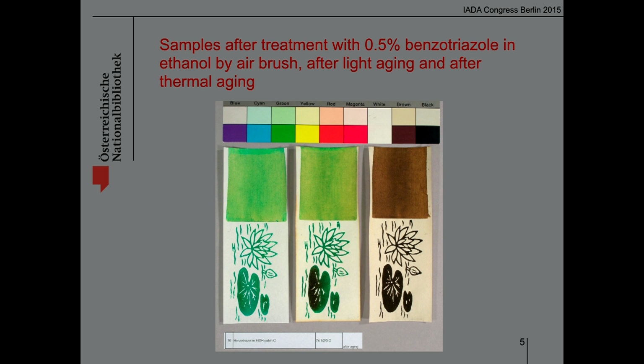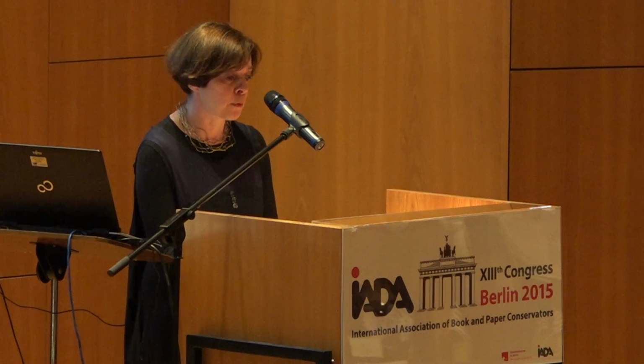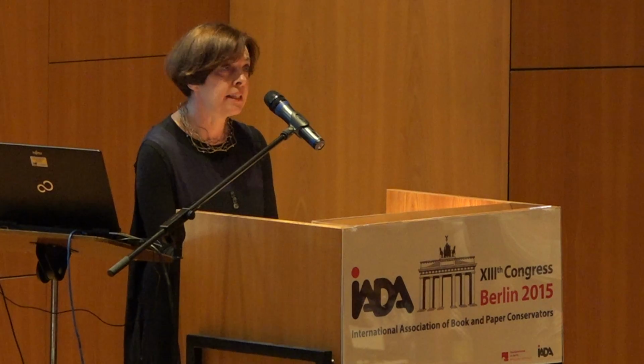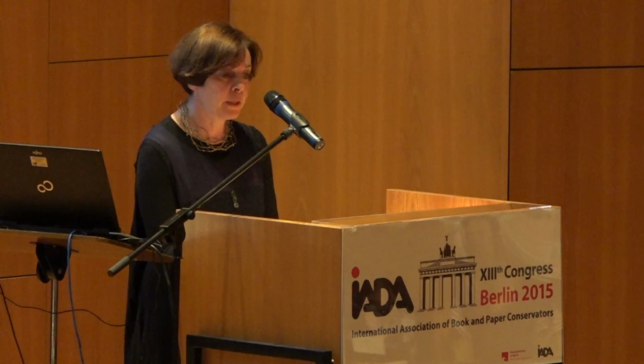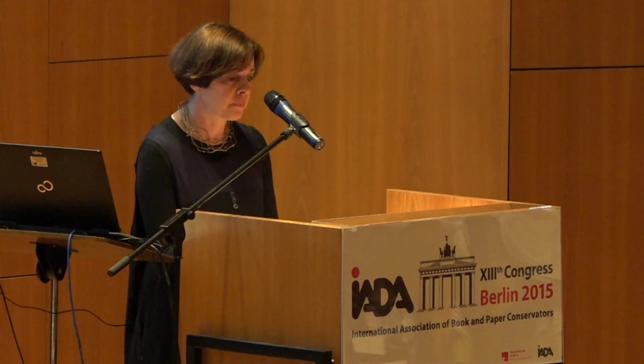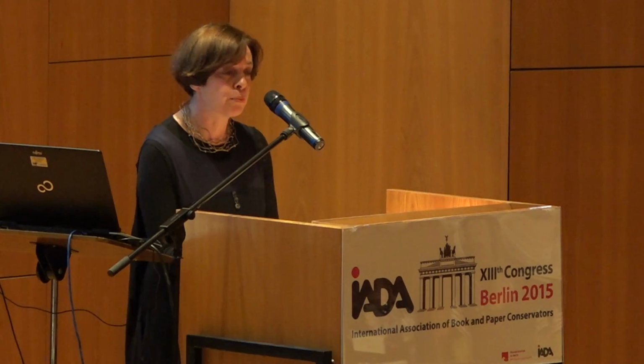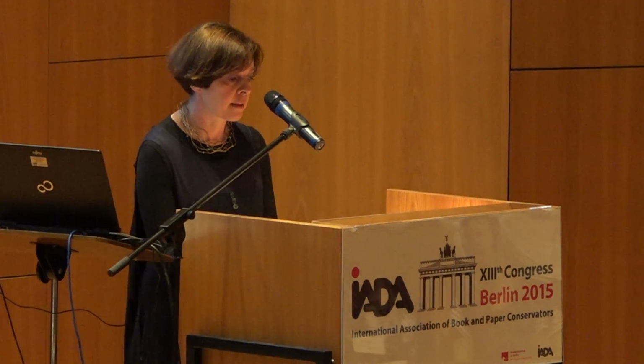After post-aging, the cellulose was analyzed by gel permeation chromatography. For mechanical stabilization, Japanese tissue papers were coated with different adhesives and adhesive mixtures. The pre-coated papers were activated with water or ethanol and applied to the samples recto and verso. After aging, the pre-coated papers were visually assessed and compared.